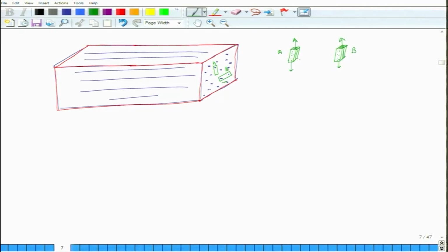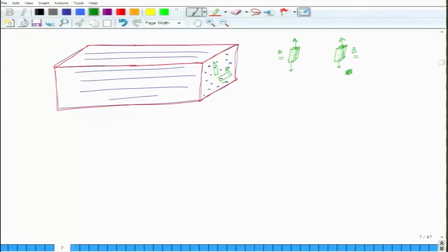And then if you test this material in tension, sample A and sample B, you will find that their material properties are the same, and you will also see that if you just pull it, it will only exhibit extensional strain. If you compress it, it will still exhibit only extensional strain. If you apply shear to it, it will exhibit only shear strain. So, this is one plane.